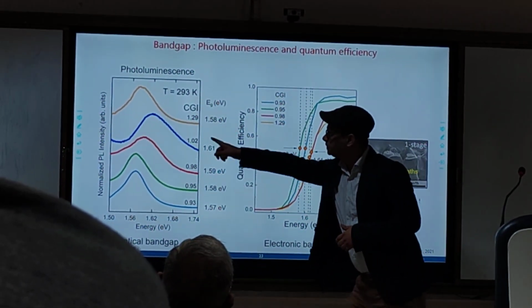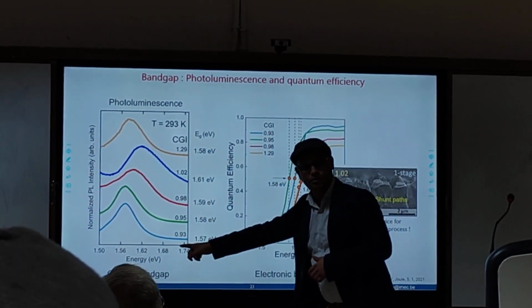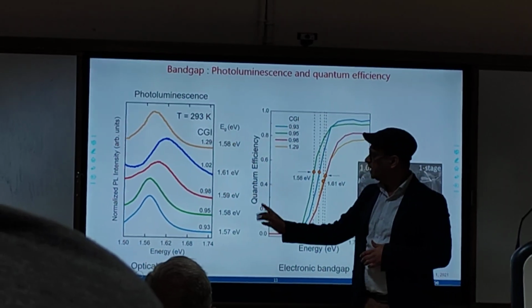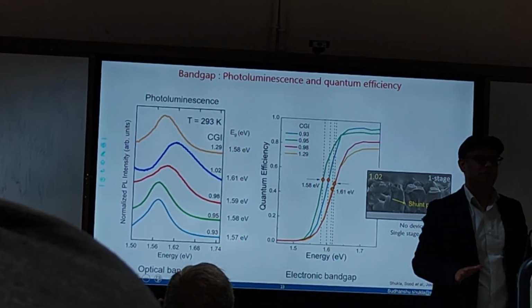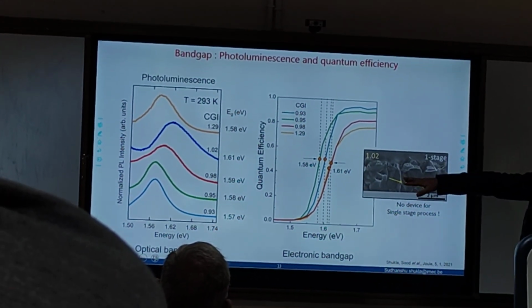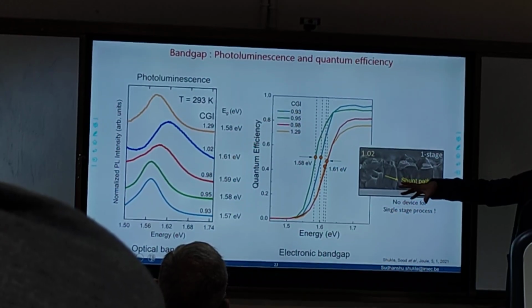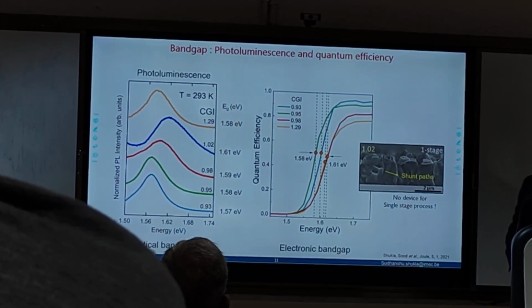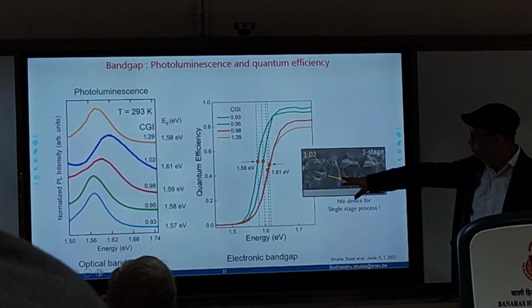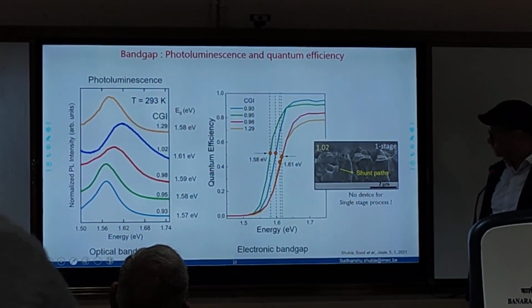Now, these are the numbers, from copper rich to copper poor. More or less, their band gaps were not so different, still in the range of 1.6, 1.59. So they were still the same, the only thing that was different was copper deficiency. The same thing we confirmed from the quantum efficiency measurements, the band gap.